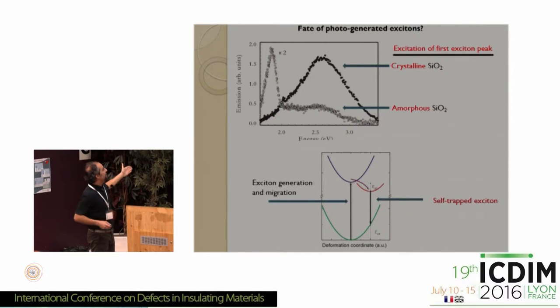And it has a very huge Stokes shift, because excitation at 10.4 gives rise to emission at 2.7. So this cannot be, of course, the emission from the free exciton. Some huge degree of structural relaxation needs to be involved to explain such a large Stokes shift. So this is due to the self-trapped exciton in SiO2.